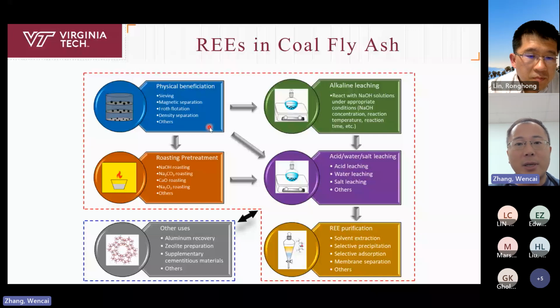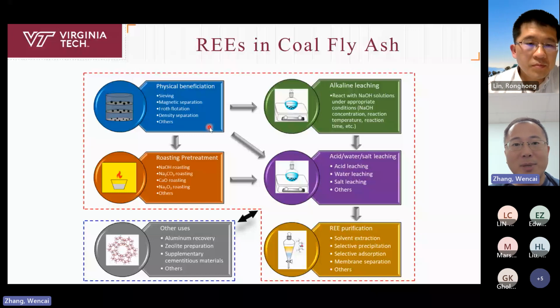This is meaningful. For example, if you do the physical beneficiation, you increase the rare earth content from 500 ppm to 1000 ppm, which means that if you use the same downstream separation and purification procedure, your overall cost to produce a certain amount of rare earths will be reduced by half. So that's the reason why it's so important. And after you get that fraction, you have different options.